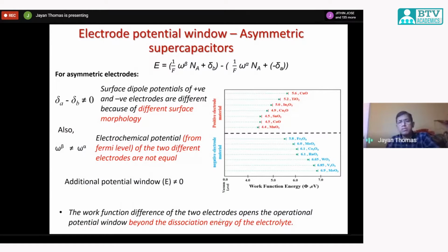So what is the take-home message from here? The message is this: by suitably or intelligently optimizing the material work function, you can get a higher voltage window than that 1.2 volts or so. If you can tune the work function of your material, and there are many methods to do that, you can get a voltage window higher than 1.2. And in my lab, by doing some modifications, we were able to get, right now, these are unpublished reports, more than 2.4 to 2.6 volts.